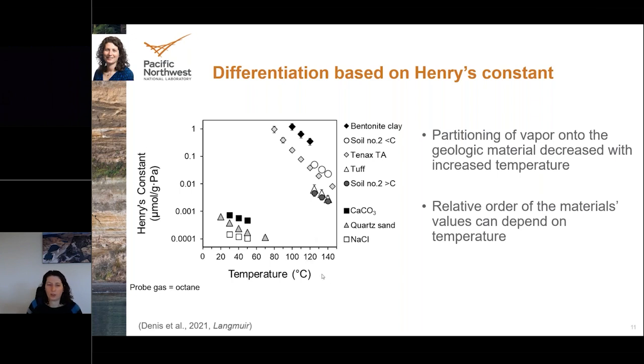onto the solid material. Overall, the materials were divided into two groups again, and in this case, we have the more absorptive materials having the higher Henry's constant, and then the less absorptive materials like the calcium carbonate, salt, having the lower Henry's constant value. And then one thing I do want to note is that the relative order of magnitude values can depend on temperature, since each material has slightly different trendline slopes.